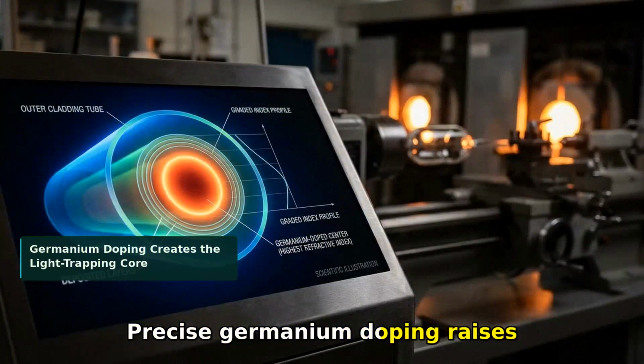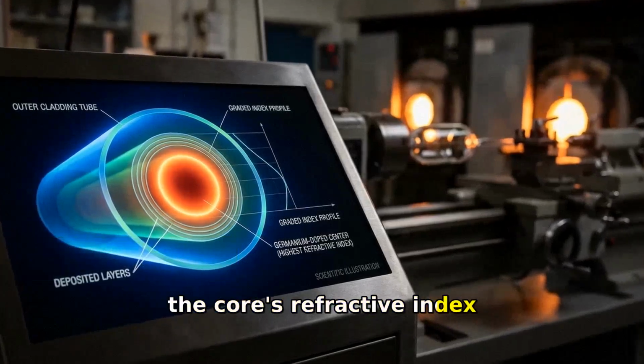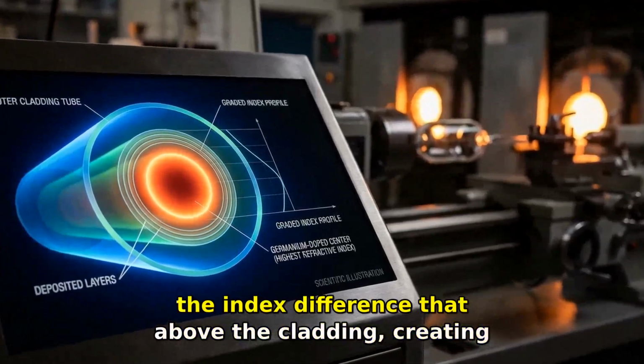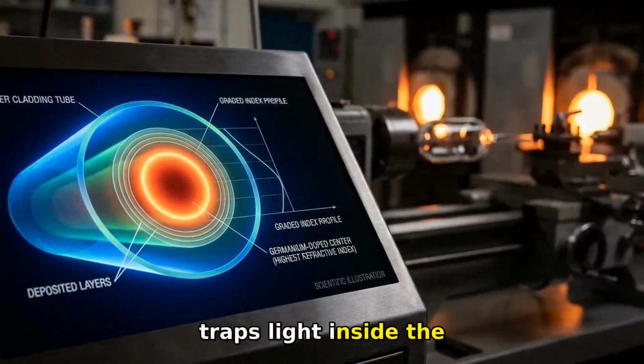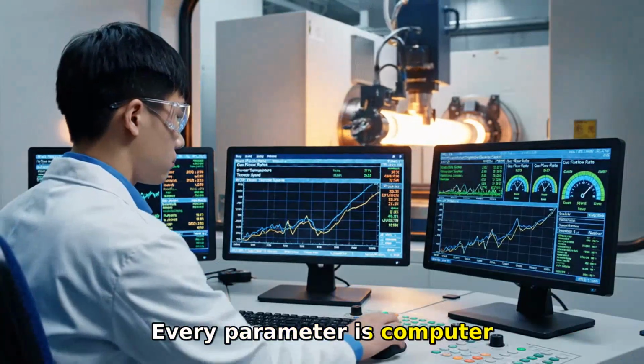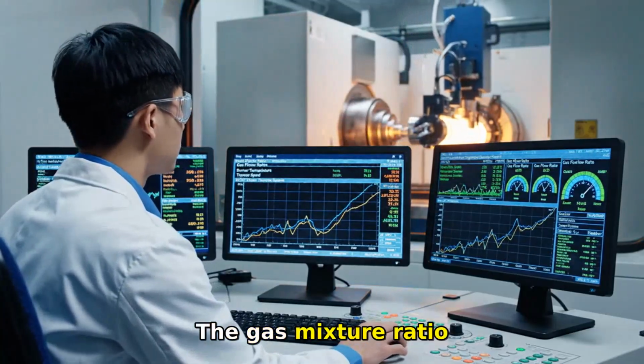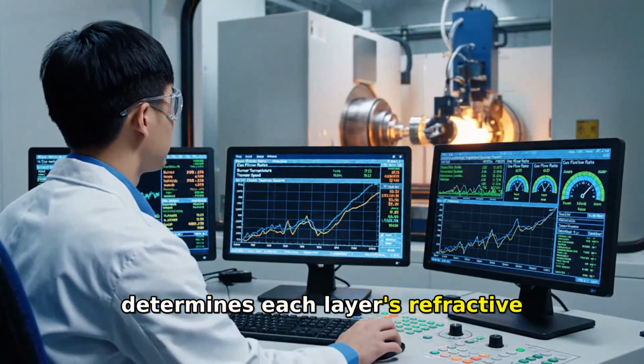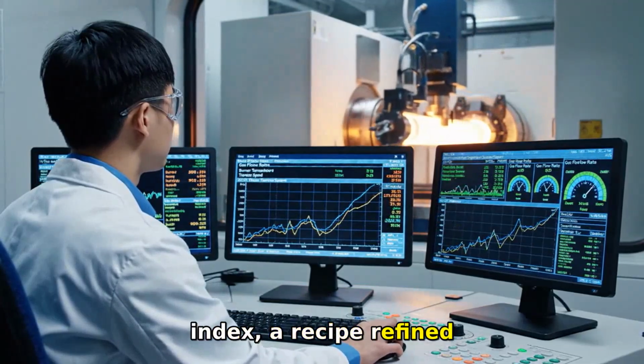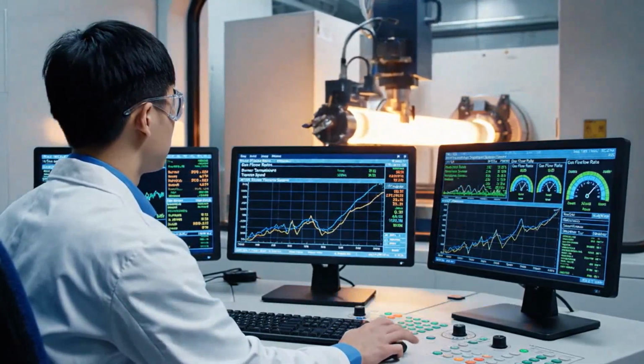Precise germanium doping raises the core's refractive index above the cladding, creating the index difference that traps light inside the fiber. Every parameter is computer-controlled. The gas mixture ratio determines each layer's refractive index, a recipe refined through decades of optimization. The refractive index profile is the preform's DNA.